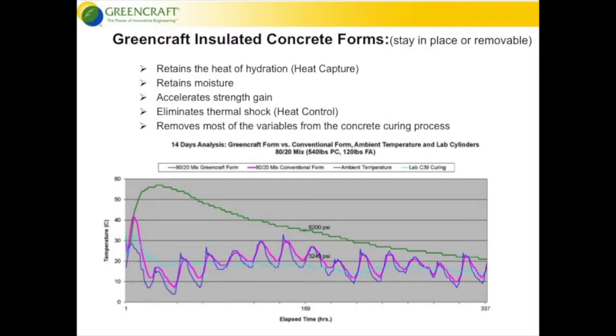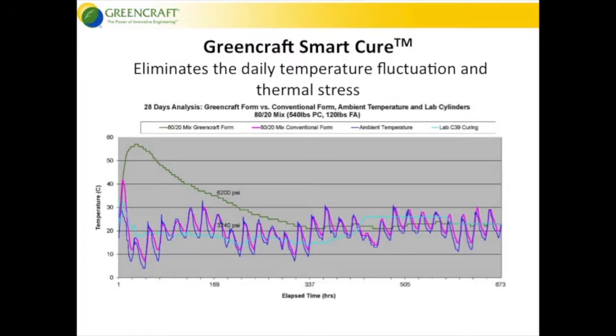This was done in the springtime in April. So you have average weather. You can see the ambient temperature. We got down to the 40s a couple of nights. Generally 50s at night, perhaps like California weather. So we call this the smart cure. Retain the heat of hydration, eliminate the thermal stresses and the daily temperature fluctuations. At 28 days, you start seeing in this chart a pattern where, while in a conventional form you have these tremendous swings of temperature, in that insulated form, unless you have some major shift in the weather pattern, you pretty much stay within 1 or 2 degrees Celsius from day to day. So this is another picture of the morning after.